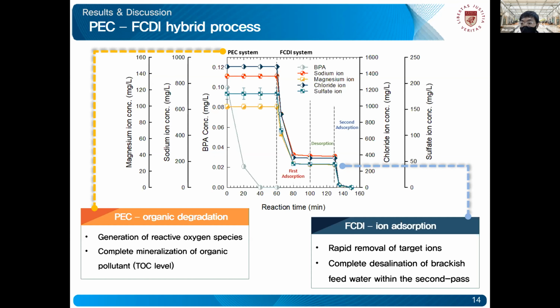So that's why in the beginning of my presentation, I said that this hybrid process was compared to nanofiltration. Now, I don't have the exact values prepared today, but for the PEC system, we found that the energy consumption was very low, around 0.02 kilowatt hour, very low compared to conventional membrane systems. Also for the FCDI system, it was very low. As I said in the beginning, under a 4,000 PPM freshwater concentration standard, the FCDI shows even lower energy consumption compared to RO. So if we compare it to the NF system, it will also be very low. So in terms of energy consumption, we found that this hybrid process has its strength and it's feasible for operation. All right, thank you.